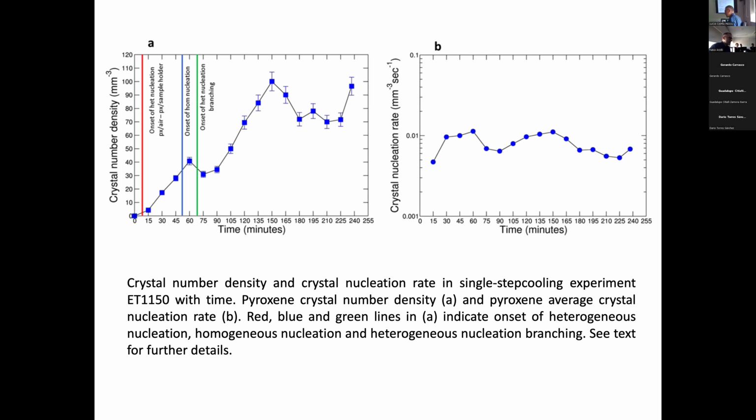Nucleation is not just one event at the beginning, like we introduced before. You impose your undercooling conditions and you have an incubation time, but the incubation time doesn't mean that it's valid for a unique event. You have multiple events, where therefore you have multiple incubation times. It depends.